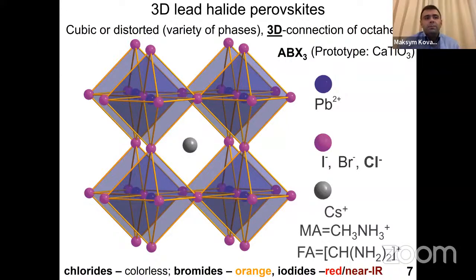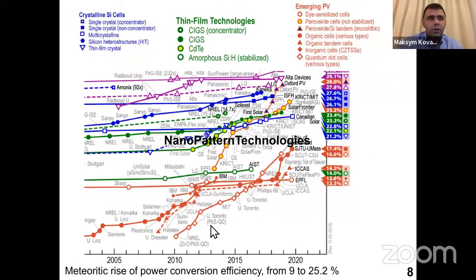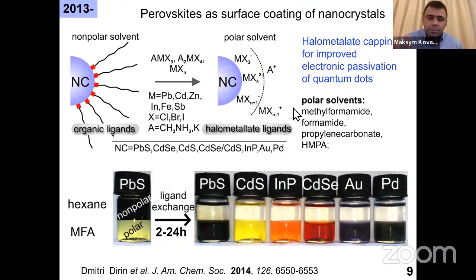Now, those again have band gap tunable across the visible spectral range here by composition in the bulk form. So basically the power conversion efficiencies of this perovskite-based absorbers have become comparable to the classical semiconductors such as gallium arsenide, silicon, and cadmium telluride. And so back then, in 2013, we understood that inherently halides make for a good semiconductor.